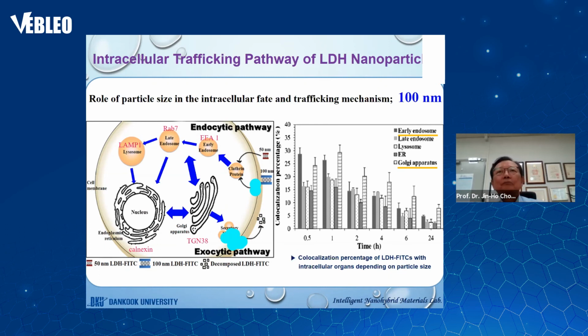So now probably you were very suspicious how our antisense gene could be very effectively internalized inside the cell without any lysosomal degradation. But here we have the answer. The 100 nanometer particles will really play a role as the delivery carrier for gene delivery, antisense delivery, because many of the antisense will actually escape from the degradation of lysosome.